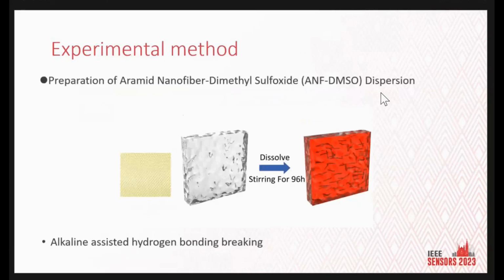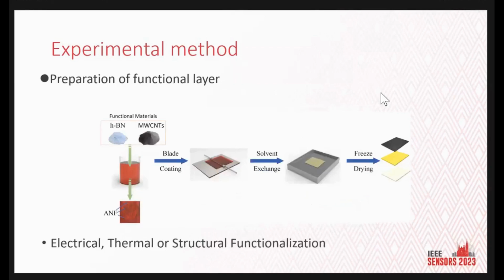We use Kevlar textile as a base material for the aerogel, and we use an alkaline-assisted method to break the hydrogen bonding in a strong polar solvent, DMSO. Then we thermally or electrically functionalize the aerogel film by adding functional nanofillers such as boron nitride or carbon nanotube into the dispersion, and we use the blade coating method on glass bases and immerse them into water for solvent exchange to remove the residual solvent. Finally, we freeze dry them to obtain a single layer aerogel film.